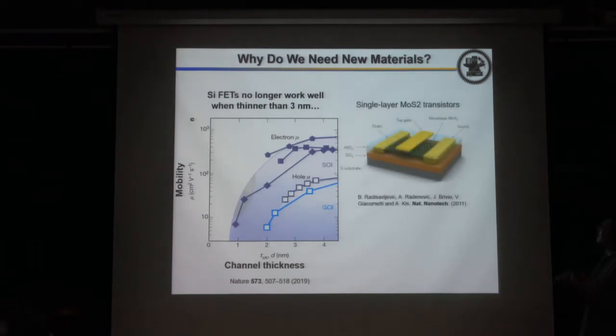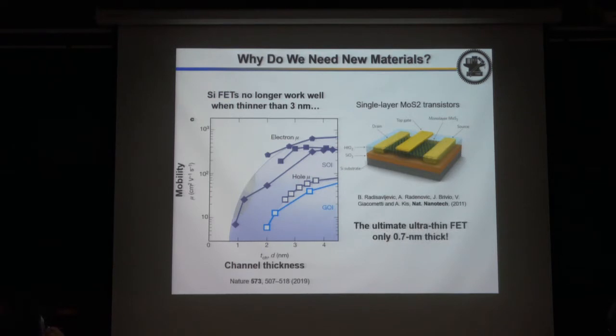So 2-dimensional materials like this, you may have heard about many times. Like MoS2, this is a 2-dimensional material. This kind of 2D material has no dangling bonds at the surface, so carriers can move freely in this kind of material. And then the ultimate thickness is 1 monolayer, only about 0.7 nanometer thick. So this is a very good opportunity for very thin FET structures. So let's check the mobility. You see, this is MoS2, MoSe2, or WS2. This kind of material actually has much better mobility than silicon at the same thickness. So once you want to reduce the thickness, 2D semiconductor is a very good opportunity.